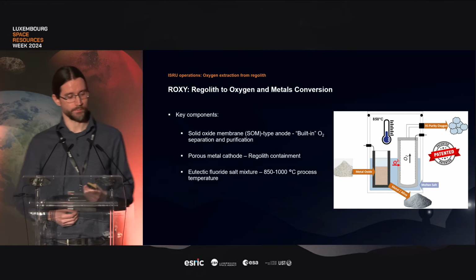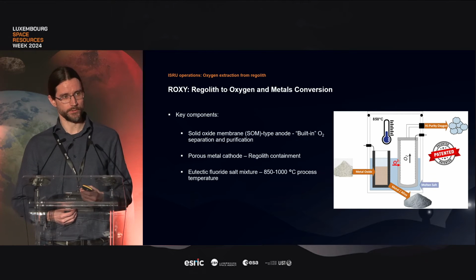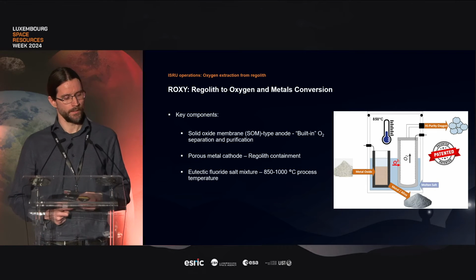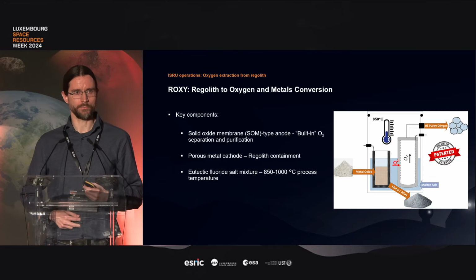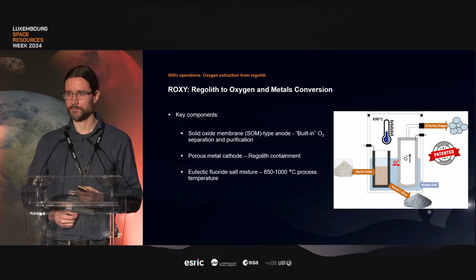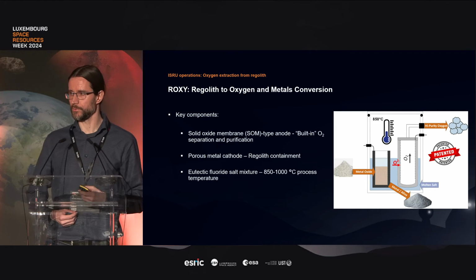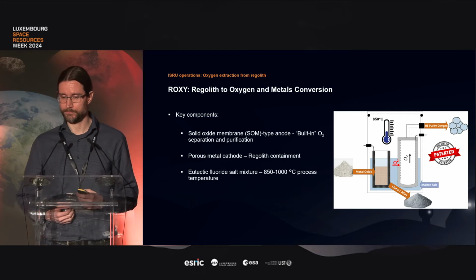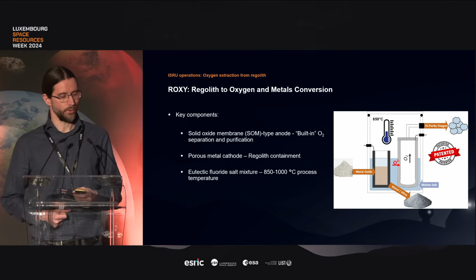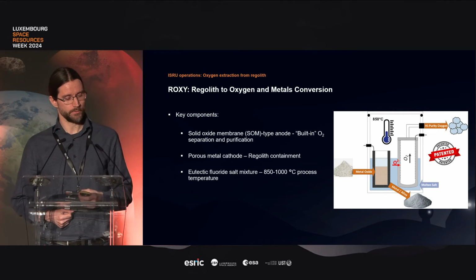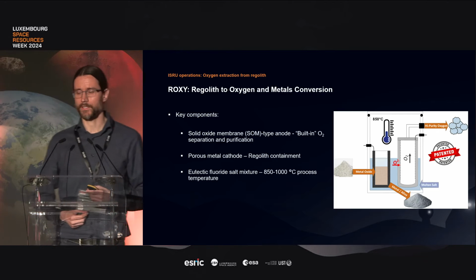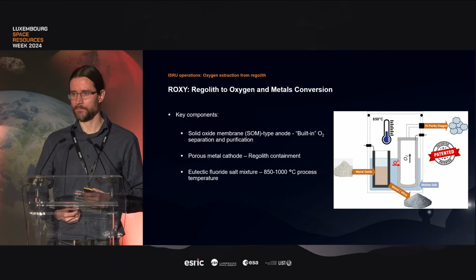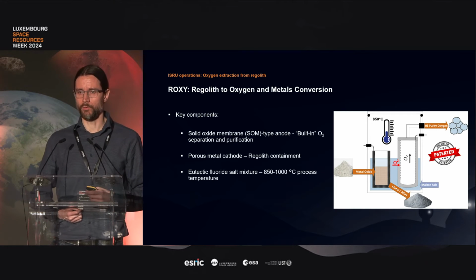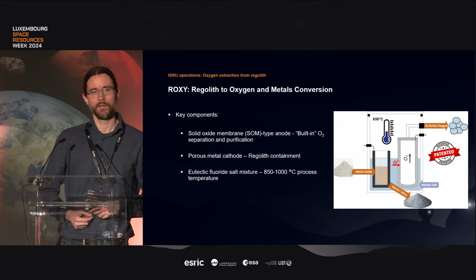The second important component is the porous metal cathode, which you can see on the left-hand side. This is an open porous metal structure, which is mostly in the responsibility of IFAM. And this is working on the one hand for the regolith containment during the process, and also the retrieval of the reduced material after the electrolysis is finished. And finally, we also have the eutectic fluoride salt mixture, which is made for processing at 850 to 1000 degrees Celsius, and which was developed to be compatible with a zirconia membrane.